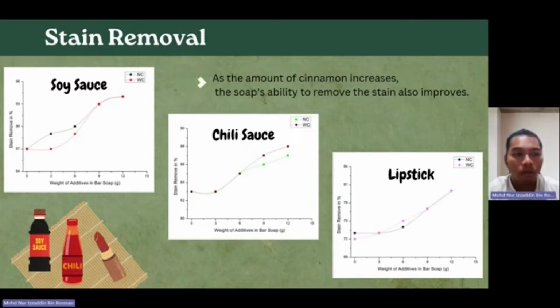for samples NC00 and WC00, 87% of the stain is removed, and it increases as the additive increases. For samples NC12 and WC12, the percent of stain removal is around 94%. This shows that as cinnamon increases, the ability to remove stains also increases. For the chili sauce, the graph shows a similar trend. Samples NC12 and WC12 have the highest percent of stain removed, around 86% to 88%. And the lipstick also shows a similar trend, with NC12 and WC12 having the highest stain removal percent.